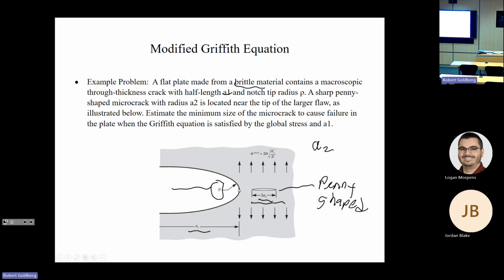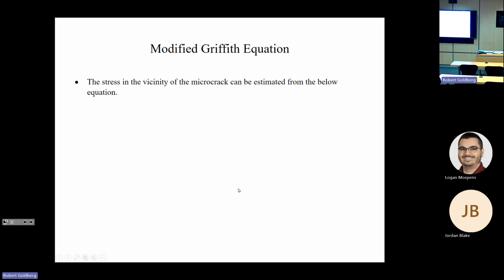Now what we're going to do is look at what is the stress right here, right in the area of the tip of this big crack. And so for that, we can say that the stress at the tip of the big crack, and this is where we use the Inglis criteria, is twice the global applied stress times the square root of the ratio of the half crack length and the radius of curvature.